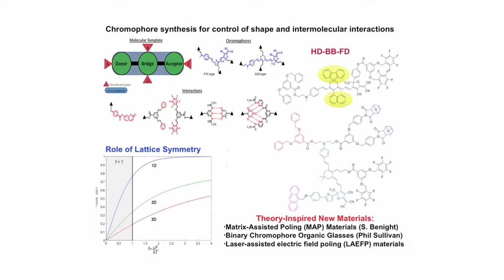And Stephanie Benight and Alex and his students have shown this to be experimentally observed. We can also modify chromophores to incorporate groups for lattice hardening. For example, we may want to increase the thermal and photochemical stability of a material by making the lattice more dense and elevating the glass transition temperature, and this can be done by these types of cross-linking reactions.